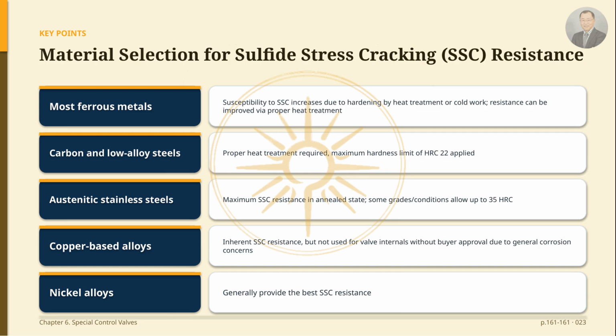Most ferrous metals become susceptible to sulfide stress cracking when hardened by heat treatment or cold work. Conversely, many ferrous metals can actually improve their resistance through proper heat treatment. Carbon and low-alloy steels must be properly heat-treated, and a maximum hardness limit of 22 HRC applies. Austenitic stainless steels have the best resistance in annealed condition, and in some specific grades and conditions, up to 35 HRC is acceptable. Copper-based alloys are inherently resistant, but due to concerns about general corrosion, they are generally not used in critical parts of a valve without the purchaser's approval. Nickel alloys generally provide the best resistance to sulfide stress cracking.